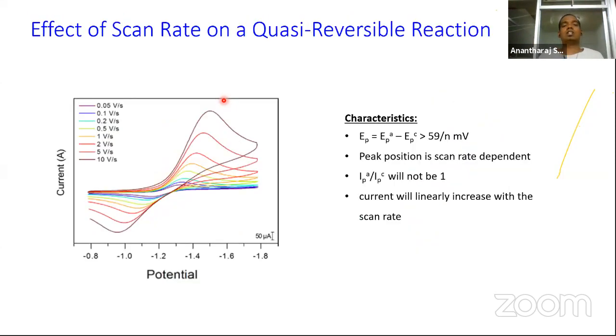Now we are going to see another type of reaction, which is called a quasi-reversible reaction, which is reversible but not kinetically so facile. That is why these reactions are called quasi-reversible. These reactions have a peculiar characteristic, which is the peak-to-peak separation. The peak-to-peak separation is always larger than 59 millivolt. From this, you can simply say the reaction is quasi-reversible. Even at a very low scan rate, the peak-to-peak separation is as large as 150 millivolt, which is very large compared to this one. So we can say this kind of reaction is a quasi-reversible reaction.